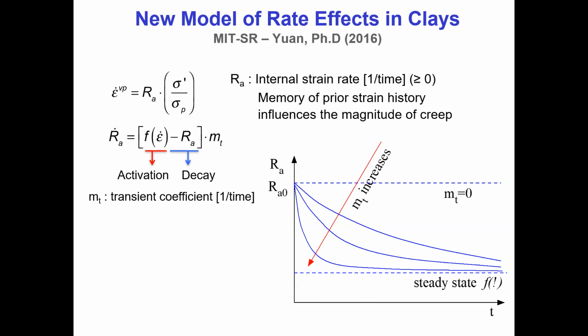The idea is that strains, or strain rates, viscoplastic strains, are related to stresses. And RA is a state parameter. RA reflects some sort of state of the material. It's like the mind state, the mental state of our clay, if you like. It's actually an internal strain rate, so units of one over time, and it's greater than or equal to zero. We use this parameter as a memory of what has happened to the soil. And the way this memory operates, you can see from the equation here.